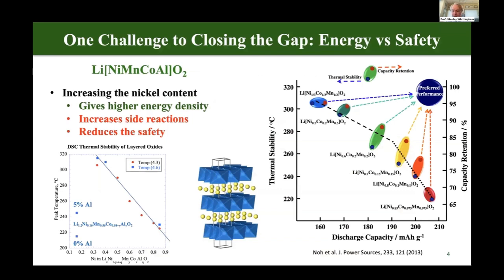So if we look on the right-hand side here, this is work from South Korea. It shows the thermal stability of nickel compounds. You can see here's the most stable one, which gives off oxygen at about 320. This only has 1/3 nickel in it and only 160 milliampere hours per gram. If we want higher capacities, higher energy density, we have to go to higher nickel. This is 85%. But now the thermal stability drops by 100 degrees. No one is suggesting the batteries are going to go to these temperatures, but these temperatures are a direct measure of how reactive these materials are with the environment, either with the air or with the electrolytes. So we know, for example, 80% nickel reacts very readily with regular ambient air to form carbonates and hydroxides. It also reacts with most of the common electrolytes. So we have to stabilize this material.